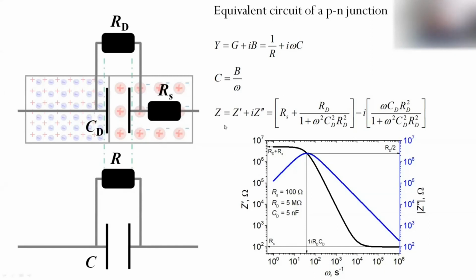In impedance spectroscopy, impedance is actually 1 over complex conductivity, it's complex resistivity. So it also has real and imaginary components, which for this particular equivalent circuit are defined by this equation. So this is some simulated spectral dependence of the imaginary and real components of impedance for this particular equivalent circuit.